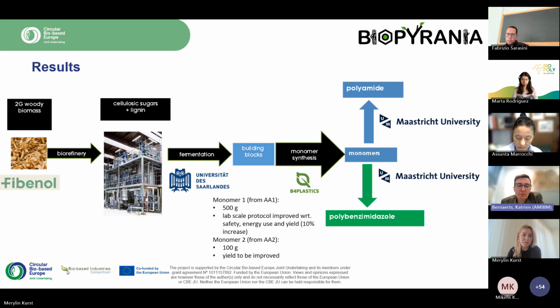B4Plastics used amino acids to make monomers. And we have two monomers. One monomer was already prepared at 500 gram scale. They seriously improved the starting lab scale protocol to the current one with respect to safety, energy use, and yield, with a 10% yield increase. And for monomer 2, we are at 100 grams scale, and the yield still has to be improved. And those monomers were used by Maastricht University to make polyamides and polybenzimidazoles. So if we go to the next slide.